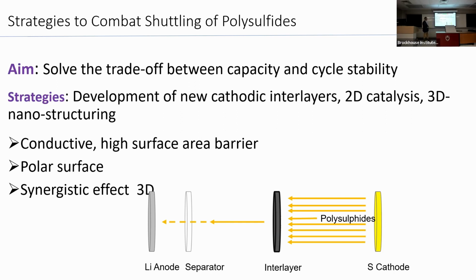It just shuttles away. So one idea for that is that you have interlayers. The interlayers have a capacity to slow down the shuttling because when it doesn't shuttle away, the electrochemical reaction takes place. If it shuttles away, there's no opportunity for electrochemical reaction. So therefore, there is a rate at which reactions take place and the rate at which it shuttles away. So we need to maximize one. Of course, for power, we want the electrochemical reaction to take place very fast. But there's a limit. It reaches its own limit after a certain level. Then we want to make sure that the shuttling rate is controlled.